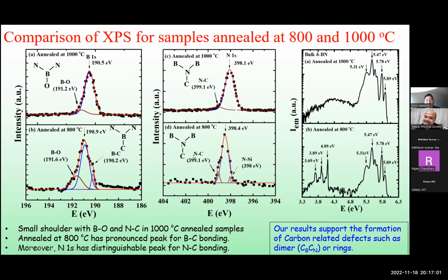And similarly, the enhanced bonding with nitrogen and carbon. So our result indicates it is definitely a carbon-related defect, and as the theoretical study says, it could be a carbon dimer or carbon ring, and more experiments are required. So we are planning to explore more with TEM of these samples. Hopefully we can see those kinds of structures, because in high resolution TEM we can see atom by atom, and we need to figure out how to distinguish whether it is carbon, nitrogen, or boron. So that's on the way. Another one on the way is measurement of the lifetime of those emission lights.